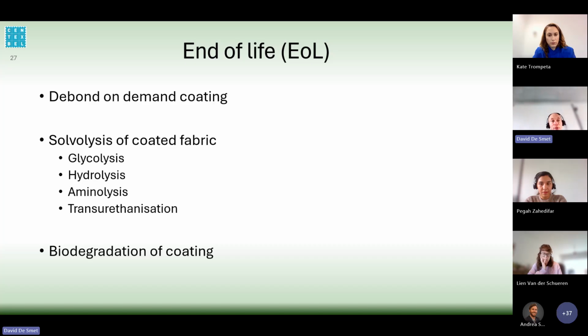So there is a debond on demand coating, which enables us to separate the coating from the textile, so which enables us to afterwards recycle the textile. Or it's also possible to do solvolysis of the coated fabric. The idea of this process is to chemically recycle the PU coating, and also to separate the coating from the textile in one step.